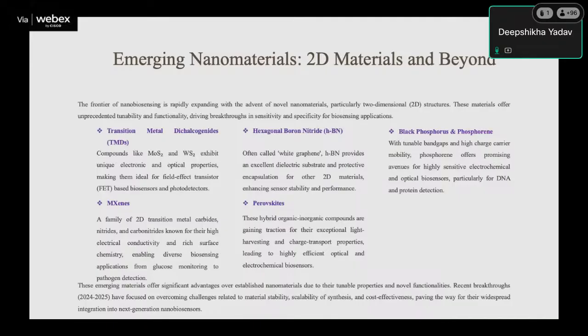Then we have the hexagonal boron nitride, which is often known as white graphene. White graphene imparts excellent dielectric properties to the biosensor surface. This is important in biosensing because in optical biosensors, this dielectric layer confines the light to the surface and generates an evanescent field which is capable of penetrating the sample only up to the 100 to 200 nanometer range. Since this field is concentrated at the sample surface, it helps in getting concentrated at the binding site, where the binding event between the bioreceptor and target analyte takes place. So even a very small change in the refractive index as a result of this molecular binding event can be detected.